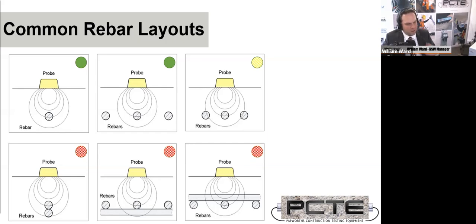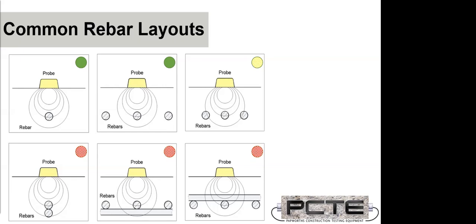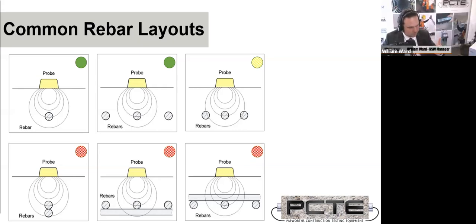If you have very closely spaced inconsistent bars everywhere, but you know your rebar cage construction, there's also scope to use a set of calibration values for particular points on that. So quite common would be in a precast segment like a Super T or something, you may choose to have three survey locations, because based upon the drawing construction you'll set up cover meter values for and measure them on. Does that help? Essentially, it's all about removing the uncertainty, and when you can't, having some way to address that uncertainty.